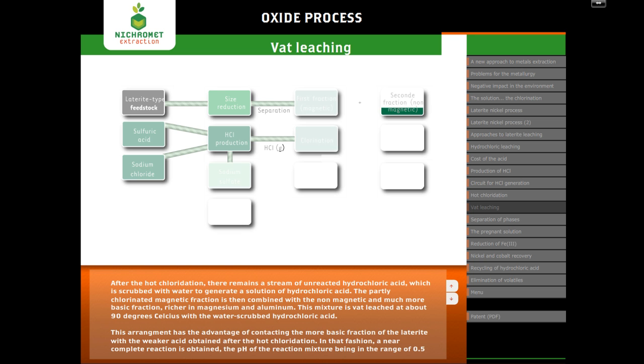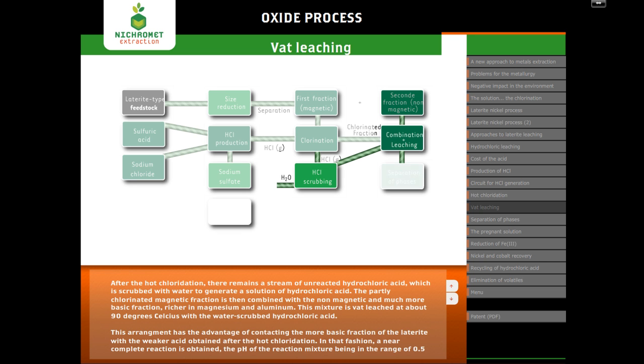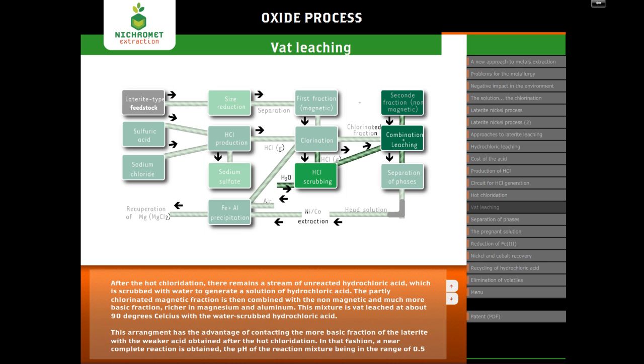After the hot chloridation, there remains a stream of unreacted hydrochloric acid, which is scrubbed with water to generate a solution of hydrochloric acid. The partly chlorinated magnetic fraction is then combined with a non-magnetic and much more basic fraction, richer in magnesium and aluminum. This mixture is vat leached at about 90 degrees Celsius with the water-scrubbed hydrochloric acid. This arrangement has the advantage of contacting the more basic fraction of the laterite with the weaker acid obtained after the hot chloridation.